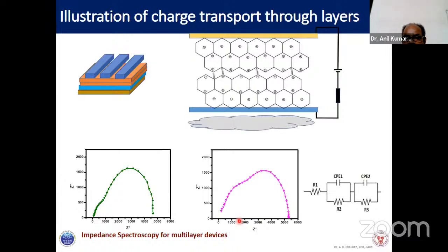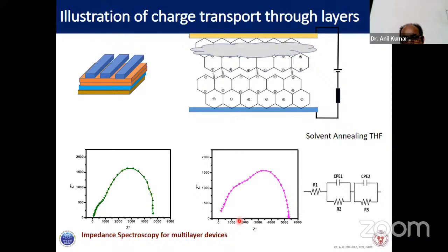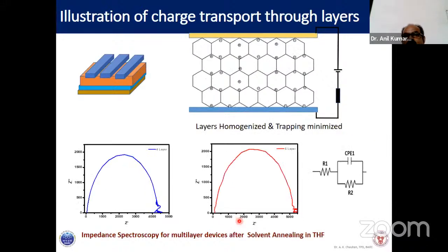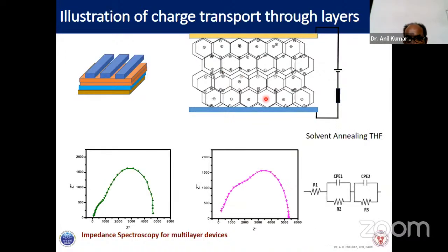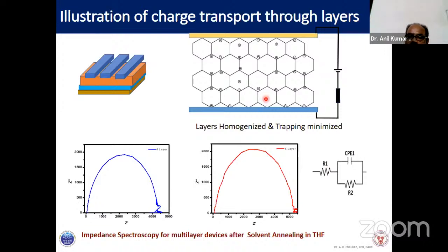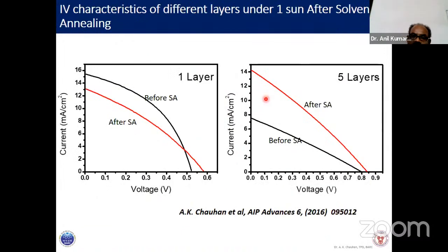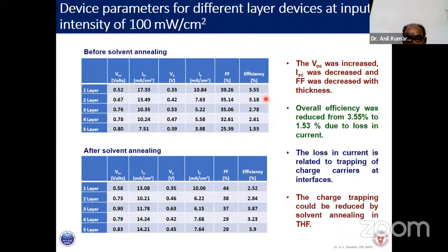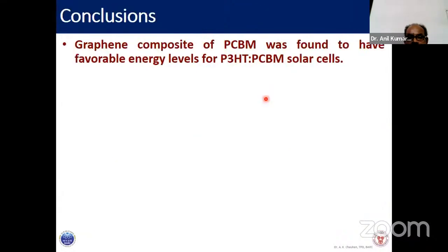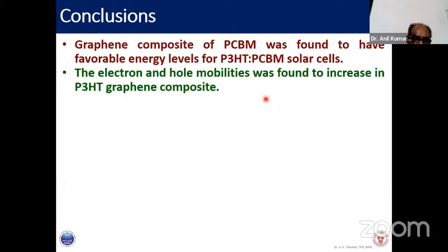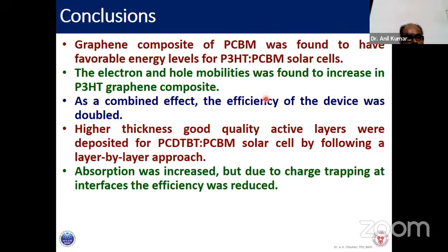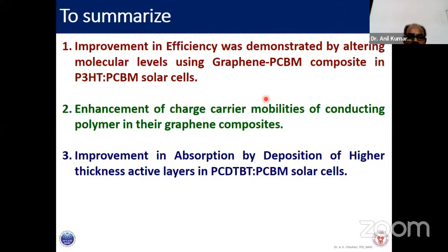So by solvent annealing, if you anneal it and expose it to the solvent, you are able to perfect the surface. And you can see it has been reduced from 2 circles to 1 circle. So by doing all these things, we effectively increase the efficiency of solar cells: by increasing the absorption, by changing the energy levels, by making graphene composites. And the third thing was to improve the mobility by these graphene composites.